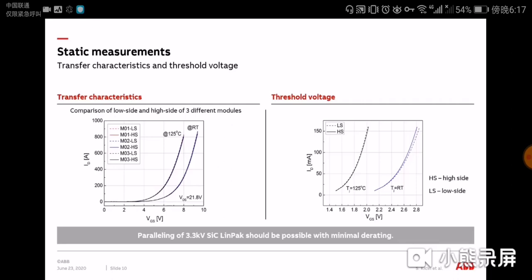One can see that the current flowing through any of the switches at any applied gate voltage differs from the current flowing through the other tested switches only by a few %. As expected, the threshold voltage was much lower at 125 degrees C compared to room temperature. Again, the difference between both compared switches was not significant. It means that our results indicate that paralleling of tested 3.3 kV silicon carbide LinPak modules should be possible with minimal derating.